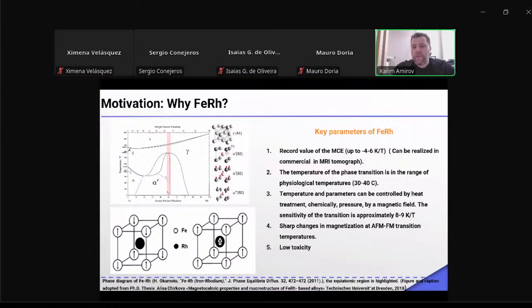It has sharp changes in magnetization, and it has a ferromagnetic transition in the heating protocol. Its structure, when heated, keeps its symmetry; the cubic structure just expands by 1%. It's also called a metamagnetic phase transition. It also has low toxicity. In preliminary biological tests it showed low toxicity, because iron rhodium is a metal from the noble group, which is already used in medical applications.